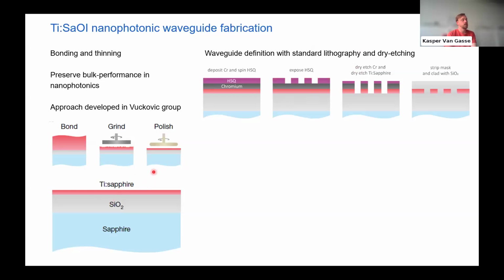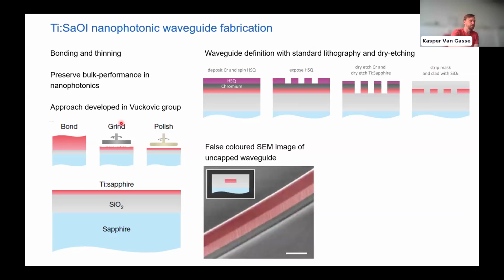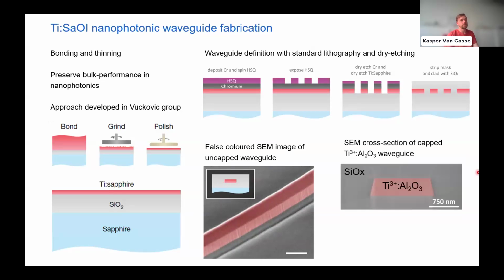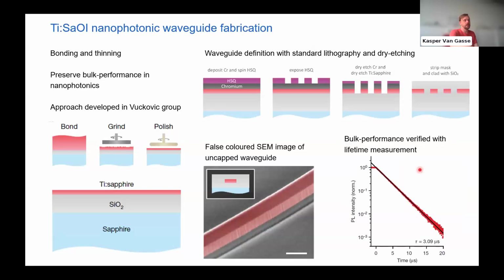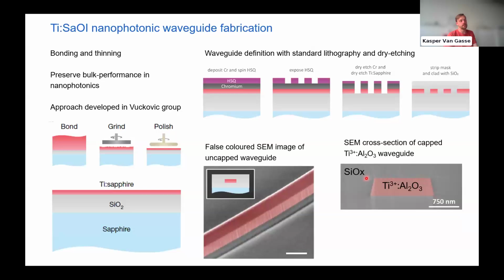So we can take this thin film and then use pretty standard E-beam lithography and dry etching to make high quality nanophotonic circuits in this layer. Here you see, for example, an SEM image of one of these waveguides. We used a false color to indicate that titanium sapphire waveguide. But in the end, it's completely capped with oxide. And here you can see a very nice SEM image of the cross-section. So you can see this is the titanium sapphire and it's surrounded by oxide. And the nice thing here is that this is a very nice waveguide that will confine both the lasing mode and the pump mode very well.